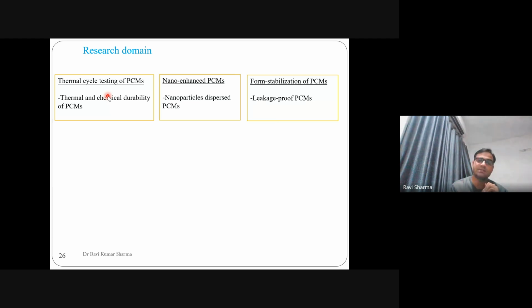Similarly, for the nano enhanced PCM, after mixing the nanoparticles or any other materials, once it is in the molten state, it will flow away. To contain it, we require a container. When we use a container, the container material might be reactive with PCM. Generally, with organic materials they don't react, but with inorganic they will react. But the container has its own weight, and it is not adding anything into thermal properties. It is simply increasing the weight of the entire thermal energy storage system. We don't require that. We don't want the thermal energy storage system to be bulky. So that's an additional burden on us.